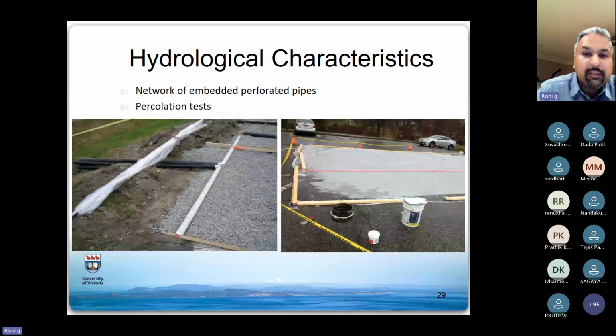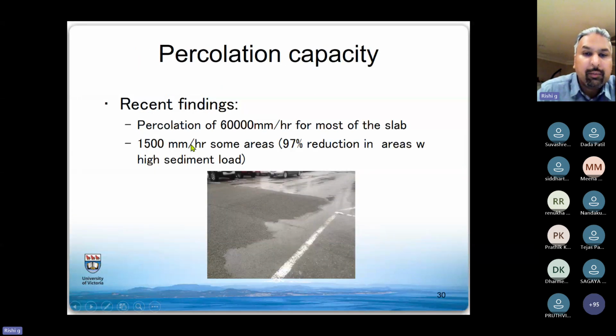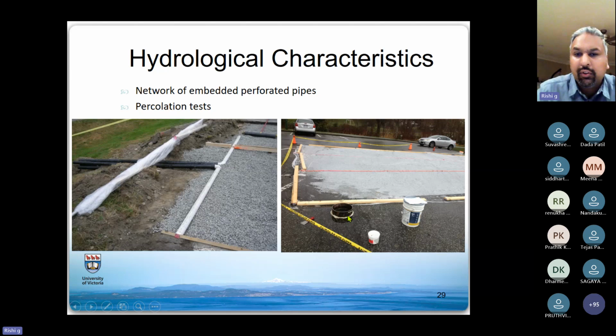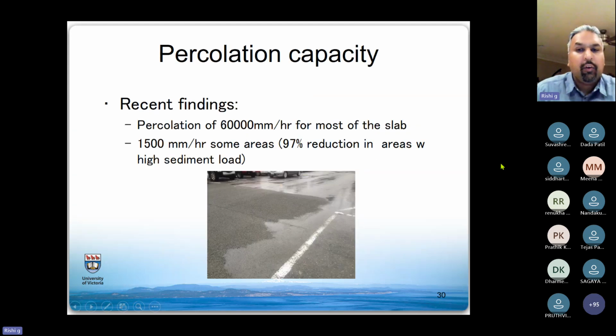So some of the percolation numbers. So you see 60,000 millimeters an hour. So these were measured. I think I had the photograph here. So these are ASTM tests. So what you do is you put a ring, you pour water in it at a prescribed rate, and you measure how much water is percolating through it over a period of time. And what you can actually do is you can calculate the percolation capacity of the porous concrete.